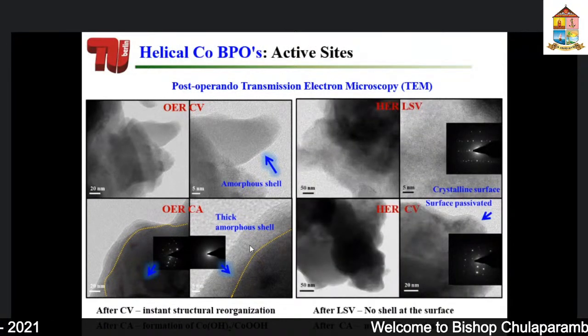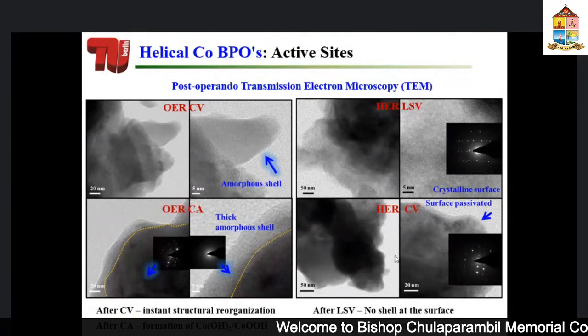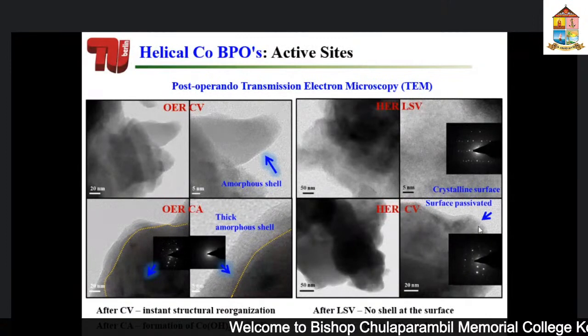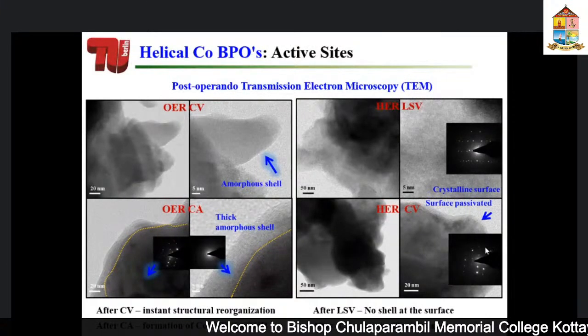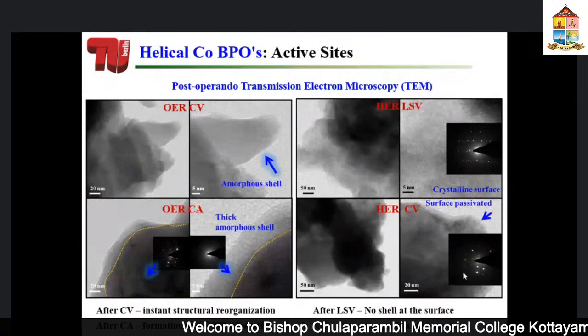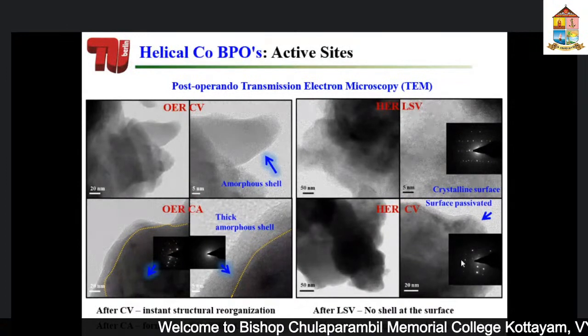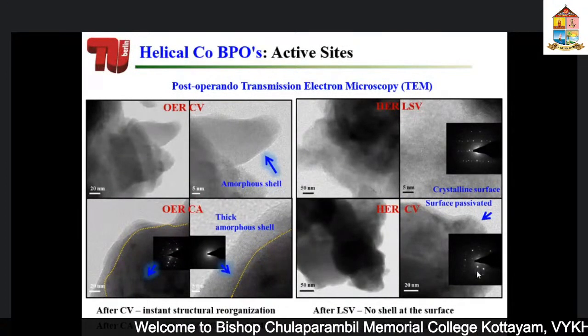Similarly, we also found that in the case of hydrogen evolution reaction, they don't change to a great extent. But what you could see is that they are surface passivated. There is some change on the surface of the catalyst, and also they remain crystalline, as shown by the intense spots of the electron diffraction pattern.